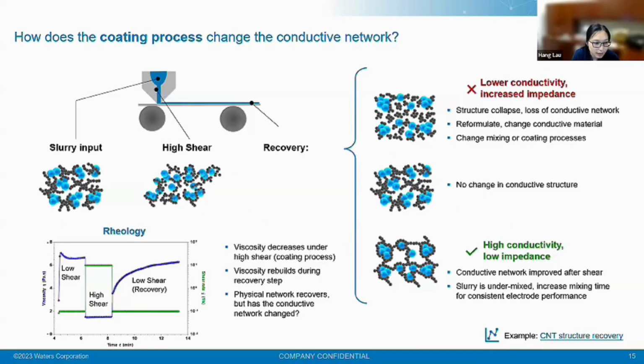And go back to the three-step thixotropy testing. When you're breaking down the slurry recovery, oftentimes the slurry recovery will be driven by your viscosity or active material, which is a larger component of your slurry formulation. Conductive additive is oftentimes very minimal in content, but the recovery of the conductive additive could really be scaling and breaking down, or could be aggregating together, not forming a good conductive network.